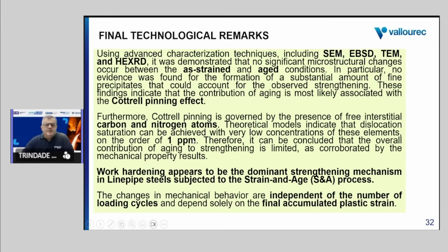And finally, work hardening appears to be the dominant strengthening mechanism in linepipe steel when subjected to the strain and aging process. The change in mechanical behavior is independent of the number of loading cycles and depends solely on the final accumulated plastic strain. I think this is my contribution for the talk today.